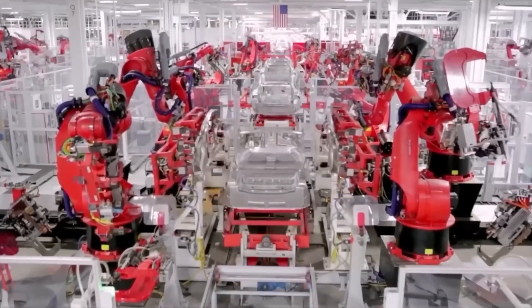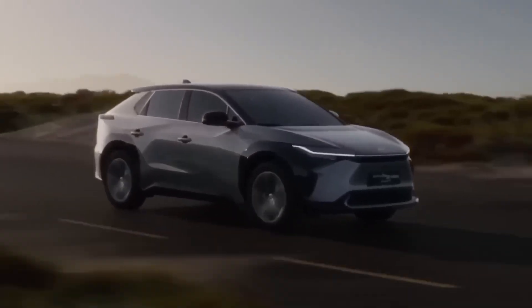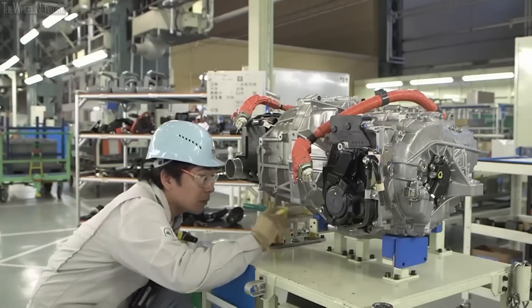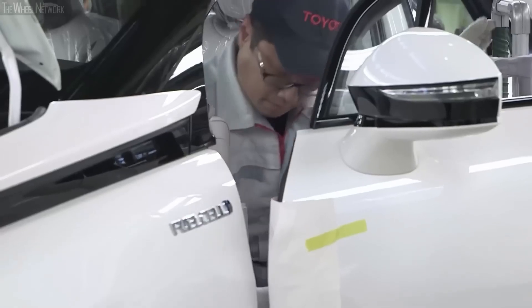While hybrid vehicles typically have smaller engines and battery electric vehicles don't use internal combustion engines, castings have historically been the most common product form, primarily used in the powertrain of ICE vehicles using secondary A380 or 319 alloys. Aluminum growth has now moved to the car body and chassis, as well as battery trays and electric drive components for EVs. Today, the majority of these components are made from sheet and extruded materials, with only a small portion from castings, which are frequently structural and made using more advanced techniques and cleaner aluminum alloys.